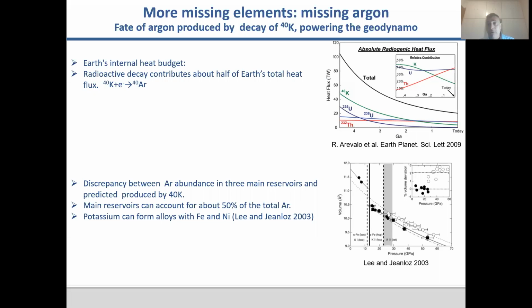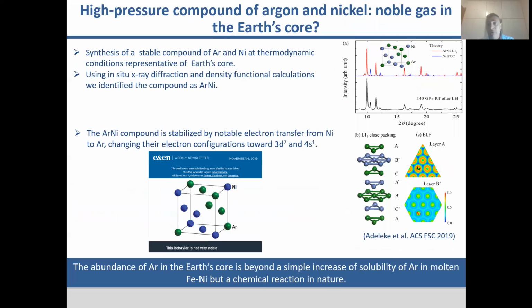Now, what's happening with this argon? According again to the models, the abundance of argon in the crust, atmosphere, and mantle is much lower than expected. Can argon be stable under these conditions? Argon is not like xenon and krypton, it's not so large. So we decided to check this hypothesis, and we aimed at nickel, mainly because we had the result with nickel and xenon. And indeed, at relatively low pressure, 140 GPa at least for this kind of experiments, we managed to synthesize this compound between nickel and argon, 1-to-1.